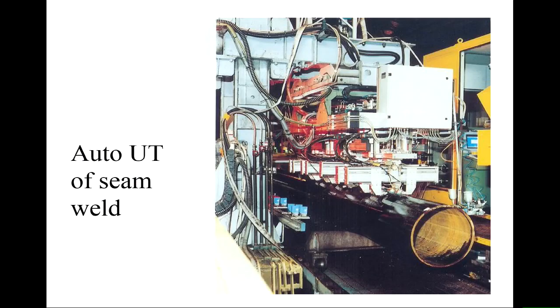So we'll talk a bit about inspection techniques later on, but this is an automated ultrasonic assessment. So you can see there's lots and lots of ultrasonic cells here. These are often used by pulse echo or phased arrays. So you're making a sound pulse, picking it up here, and looking for changes due to defects and things. And by having those arrays at different angles, you can look at different levels in the weld. So you know exactly where the defect is and how big it is, hopefully, if you do this properly.